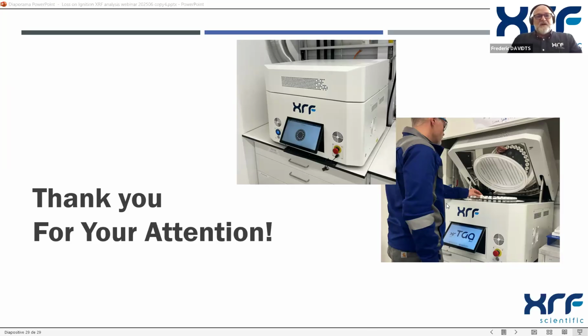Yes, of course, it is possible to do. Gain on ignition is a little more complicated to deal with, and you need to know a little about what is in your samples. The possibility to do the loss on ignition or the analysis at different heating steps allows us to determine when we have the oxidation and when we have the loss, and then we can calculate more precisely. But clearly you need to know the composition of your sample. You need to have a rough ID for sure.